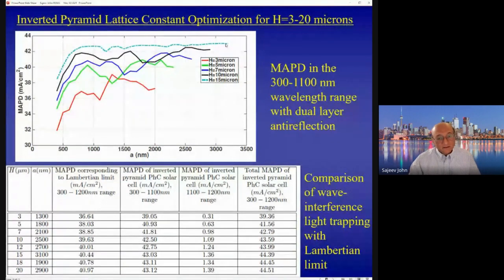And a larger lattice constant is easier for fabrication purposes. So that's what we focused on. If you go to thinner structures, the optimum lattice constant for 10 microns is 2.5 and gets smaller and smaller. So this is the MAPD in the 300 to 1100 nanometer range using a dual layer anti-reflection coating, slightly different from the 3-layer anti-reflection coating used by the experimental group.